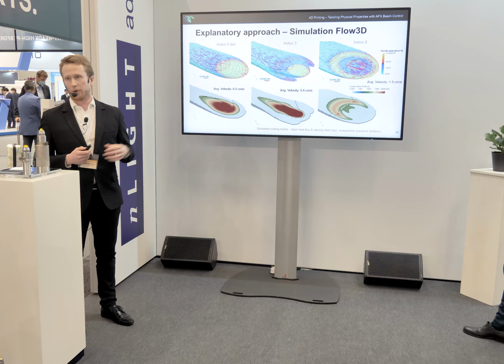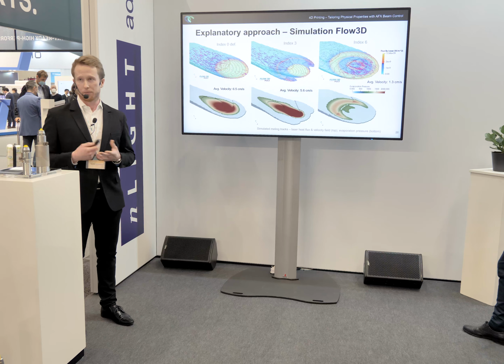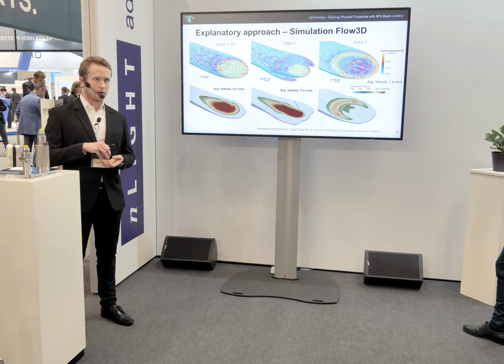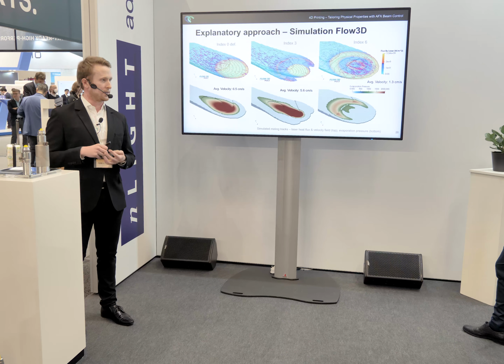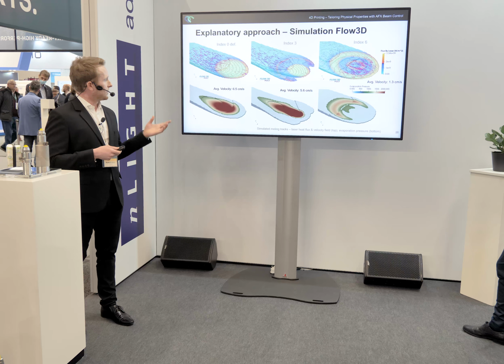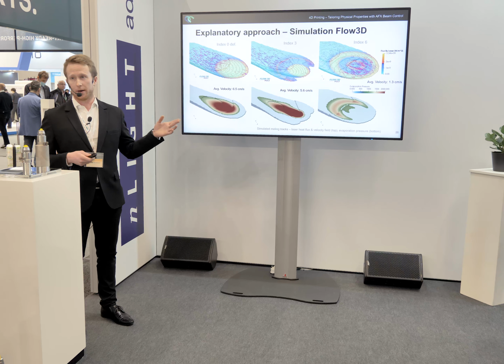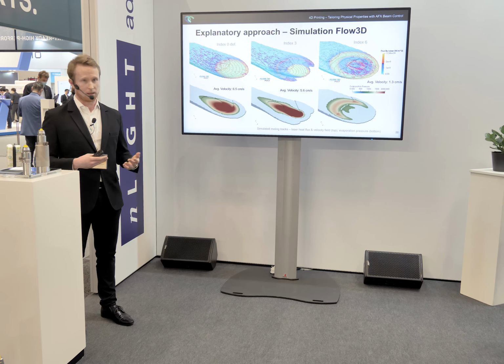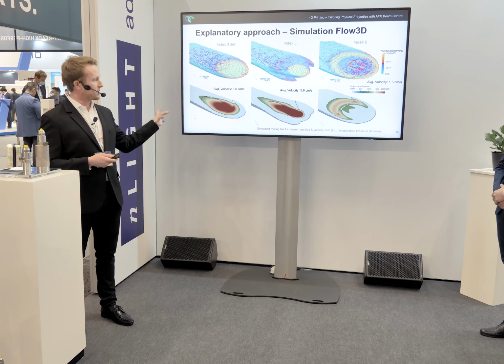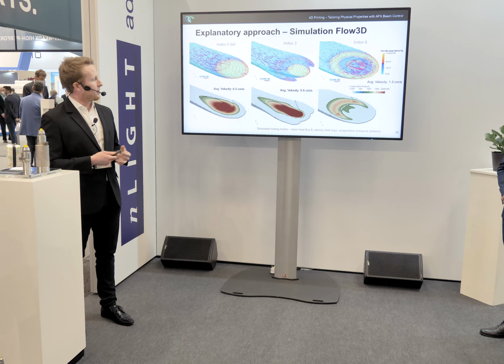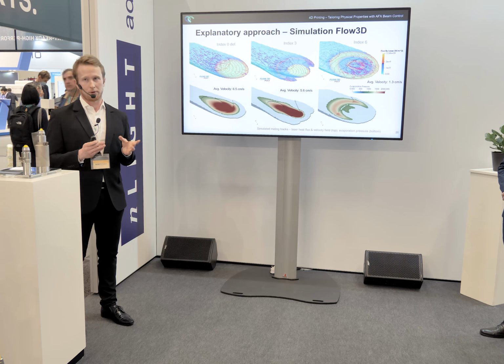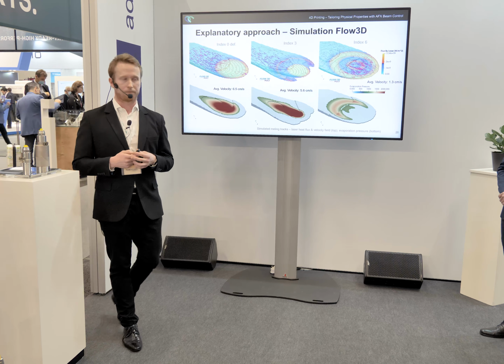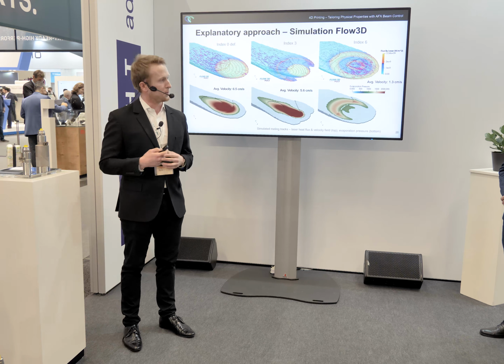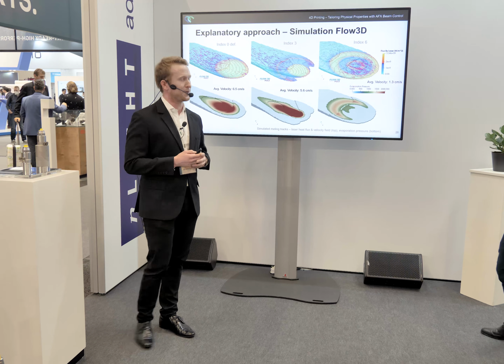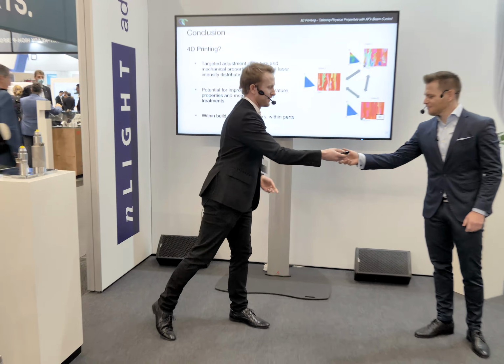And here on the bottom, what I have shown is the evaporation pressure, which, as I mentioned at the beginning, is the pressure coming from the expanding or rapidly evaporating gas at the molten interface. It is what we think is one of the main drivers for this change in the velocities, because as you can see, the maxima of this evaporation pressure are shifting a little bit to the outer ring when we change the heat flux distribution. So this will be our contribution. I'll just give the stage back to Marco to sum up our study.